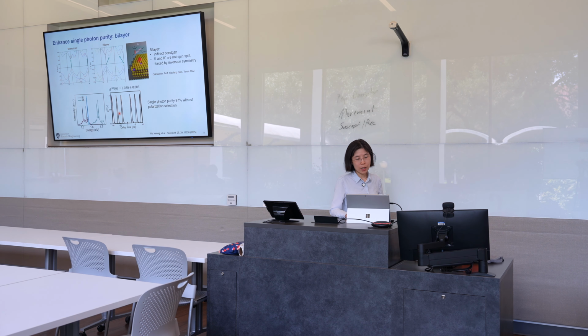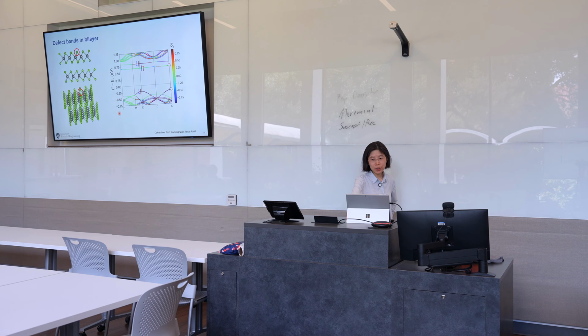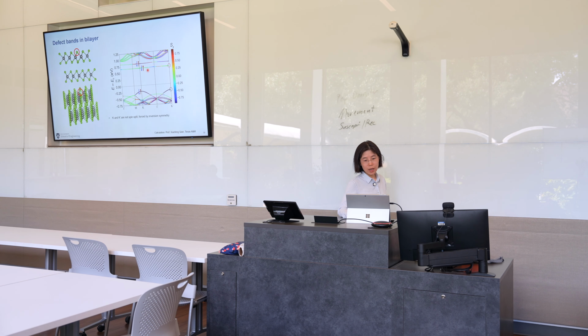So now if we look at the first principles calculations, again, these K and K prime valleys are here, but you can see they are no longer spin split, and this is forced by inversion symmetry. And we can also see these flat bands that correspond to the defects, and they are actually doubly degenerate with effective zero spin density. So they can also host excited electrons with arbitrary spin.